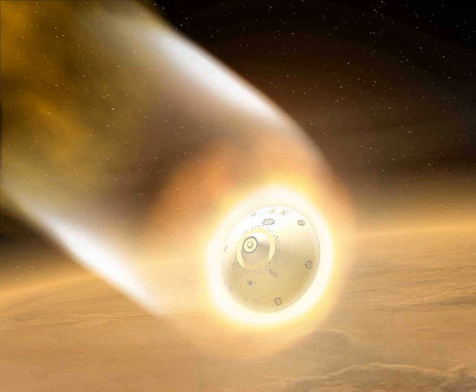For lunar return entry of 11 km per second, the shock layer contains a significant amount of ionized nitrogen and oxygen. The five-species model is no longer accurate and a 12-species model must be used instead. Atmospheric reentry interface velocities on a Mars-Earth trajectory are on the order of 12 km per second, 43,000 km per hour, 27,000 miles per hour. Modeling high-speed Mars atmospheric entry, which involves a carbon dioxide, nitrogen and argon atmosphere, is even more complex, requiring a 19-species model.